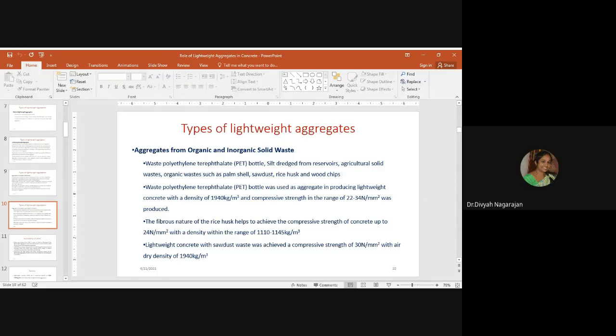Waste polyethylene terephthalate, that is PET bottles, when used as lightweight aggregates in concrete, a density of 1940 kilogram per meter cube and a compressive strength in the range of 22 to 34 Newton per mm square can be produced. The fibrous nature of the rice husk helps to achieve a compressive strength of concrete up to 24 Newton per mm square with a density within a range of 1110 to 1145 kilogram per meter cube.